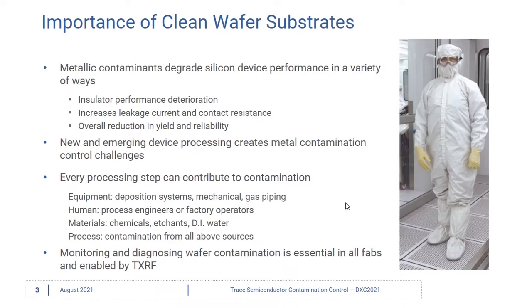Fabs want clean wafer substrates because metallic contamination degrades device performance. It deteriorates our insulators and it increases leakage current and contact resistance.